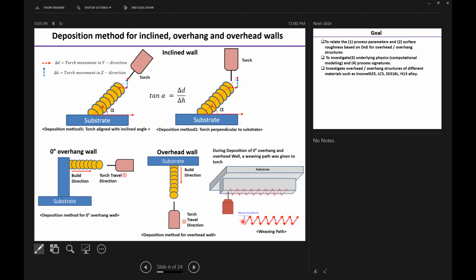So the various parameters for the weaving path are the weaving amplitude, that is the distance from the center point to the maximum height, then the weaving frequency, and the dwell time. Dwell time is the time for which the torch stays at the extreme points like this and this. That may be 0.1 second, 0.5 second, like that.